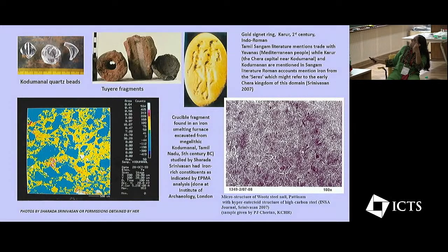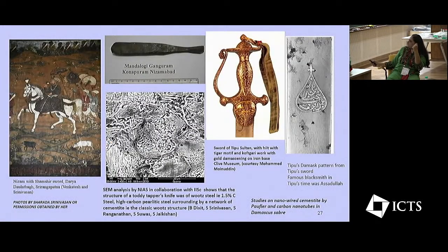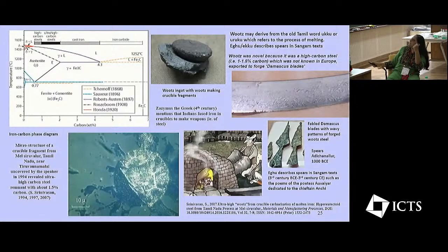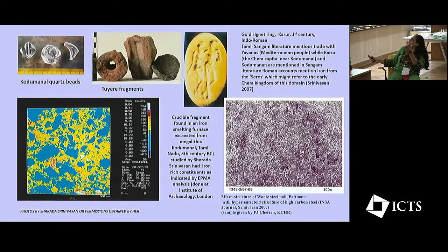And this is a microstructure of a nail from Pattanam. And what is interesting is that it has exactly the same structure that you saw in the crucible fragment from Mel Sirivallur, where you can see the remnant droplets of wootz formed here, the hypereutectoid steel, the pearlite surrounded by cementite. And that is exactly what you're seeing here.